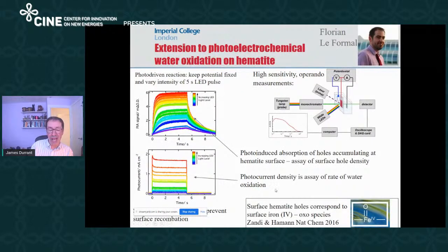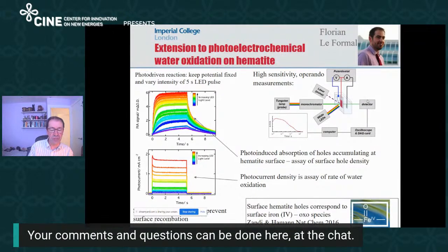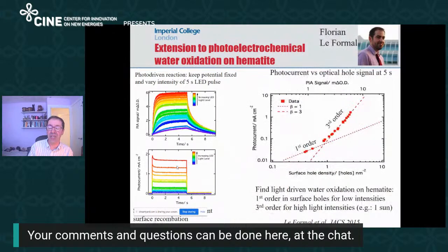That was for dark reactions. We can do the same with light. In this case, typically we don't change the potential, we change the light intensity to change the density of holes. We can measure the density of the holes optically again, and this is the optical signal of the holes on the surface as a function of light intensity. Here's the current going. These are measurements done no longer in a simple UV vis spectrometer, but in one of our transient systems. But again, we can plot the density of holes on the surface versus the current density, which we measure for water oxidation, and we plot one against the other.